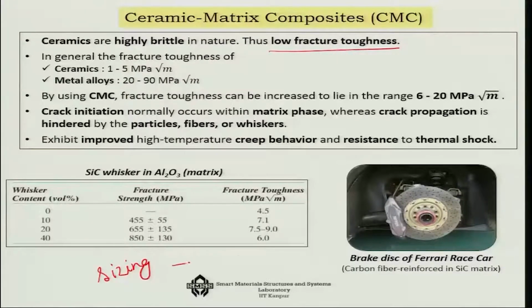Sizing means you take a ceramic fiber and then you apply an oil coating over it. What coating you are giving, that is a trade secret, because that enhances the life of the fibers and increases the fracture toughness. Now in general the fracture toughness of ceramics is only about 1 to 5 MPa square root meter, and for metal it is about 20 to 90 MPa square root meter.